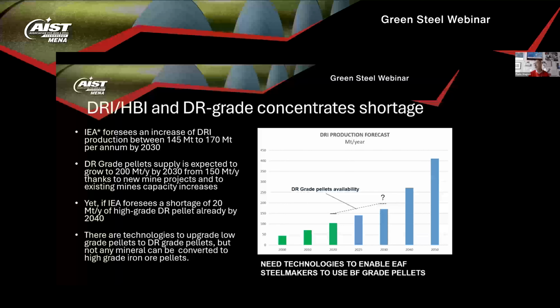Another evidence pointing to some issues with the future supplies of DRI and pre-reduced materials is that the market of DRI nowadays is in the range of 100 million tons, 120 million tons of DRI produced. Most of those tons are produced and consumed within the producing country, but we are trying to compare a market worth some 100, 200 million tons of DRI with the competing market of the blast furnaces, which consumes 1.5 billion tons of raw materials, if not more, 1.7, I would rather say. So many issues are pointing towards a lack of available technologies.